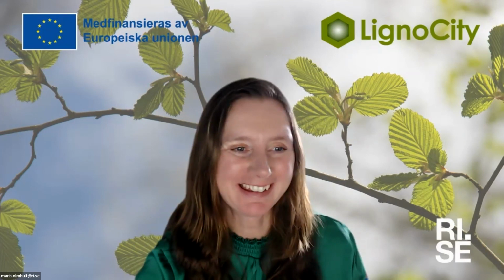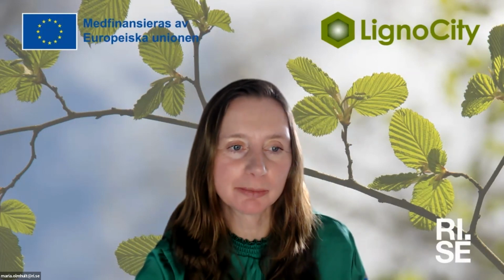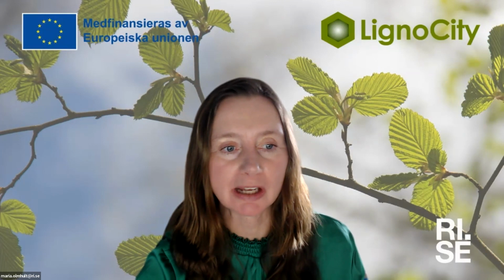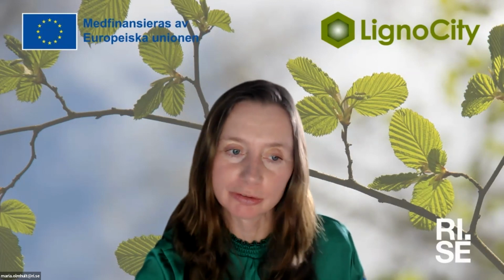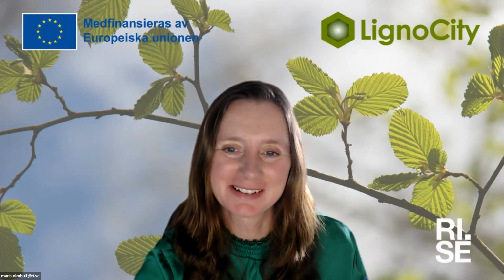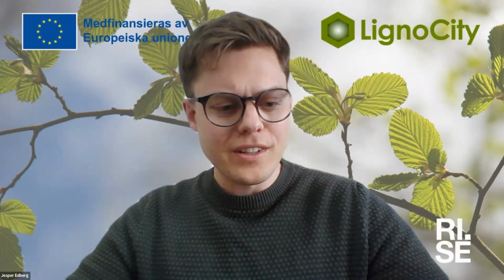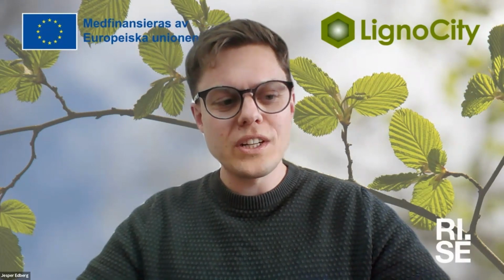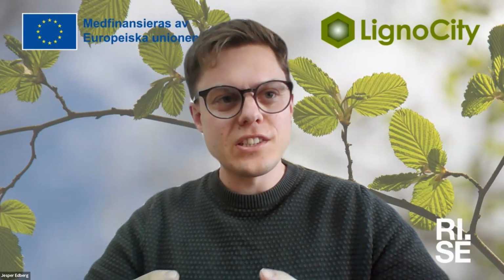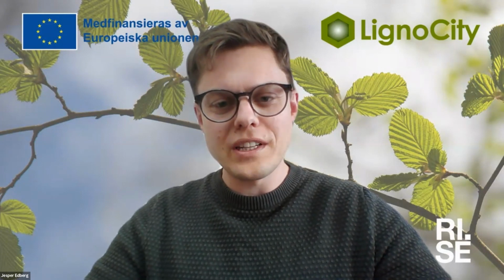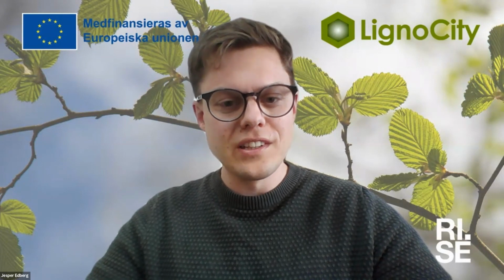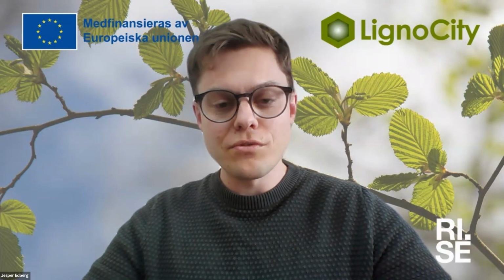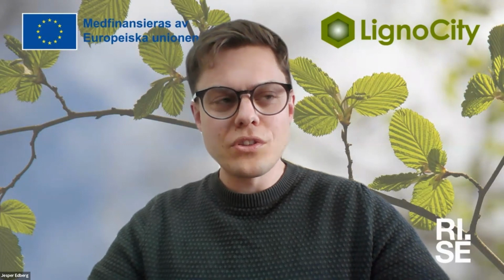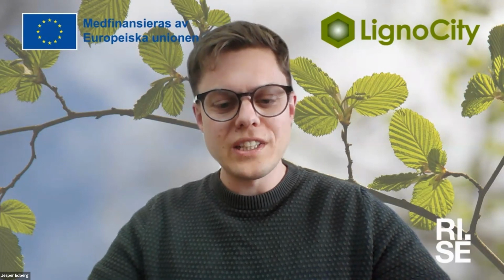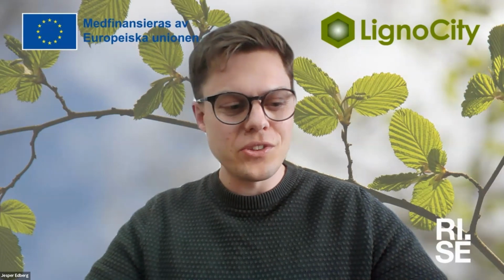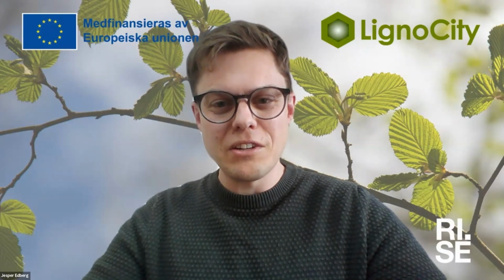Great, thank you. Are lignosulfonates better starting materials for these applications? What about other lignin sources like kraft lignin or sulfur-free lignins? Yes, I think I partly answered that question before, that we don't really know if it's the structure of the lignin itself that matters, or in our case, it was more the ink preparation. We did try to use softwood kraft lignin. We could form an ink and we could print it, but we saw that instead of graphitizing, the material kind of just evaporated. We ended up with nothing on the surface.